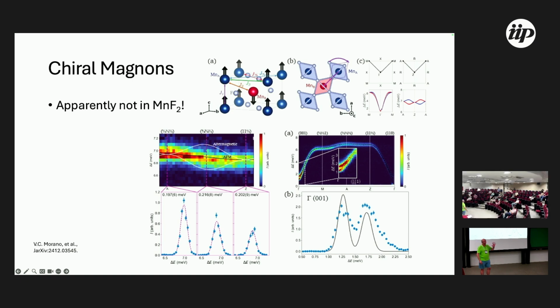Manganese fluoride really is one of the materials where the magnetic properties have been known in great detail. The nearest neighbor exchange interaction, the next nearest neighbor exchange interaction, those are things that have been measured 50 years ago. The anisotropy is really well known. You can get this from the spin flop transition and things. So the magnetic parameters are super well known. I don't recall which one of the interactions, but I think maybe these two have to be slightly different in order to generate this altermagnetic magnon band structure.